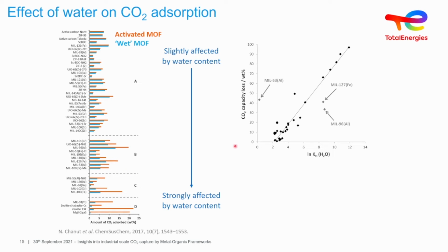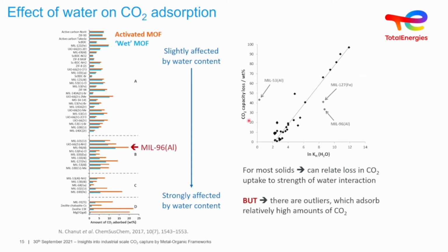What we can do here is find a way to compare a CO2 capacity loss here, so the difference between the orange line and the blue line, and then we just compared it with the strength of interaction of water with our material. In most cases, we'll have a straight line because the water takes the same sites that the CO2 would like, and there's potential adsorption of water. There are some outliers. MIL53 we think is an outlier because it's a flexible material, and it's a flexible material in the wrong direction for us.